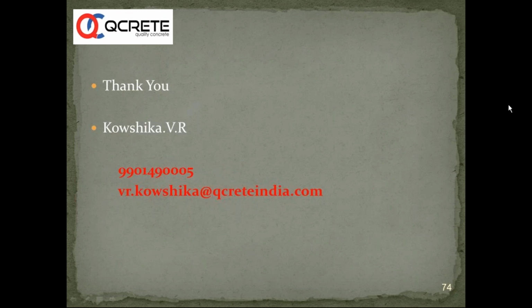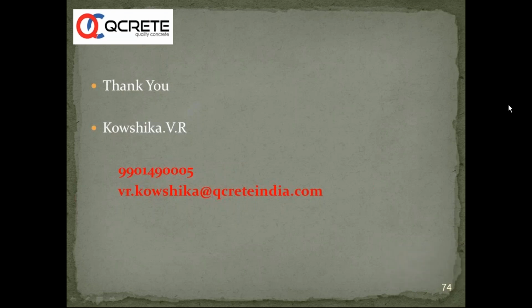What type of fly ash is available? Anaga is asking. Mostly the type of fly ash available in India is class F fly ash. Class C fly ash, which has a CaO content of more than 10%, is available only in some plants. And there is Neyveli Lignite Corporation, where the fly ash comes under class C, having a very high amount of sulfates, and it is generally not preferred by the concrete industry, but if it is ground it can be used for other purposes. So the type of fly ash predominantly available in India is class F.